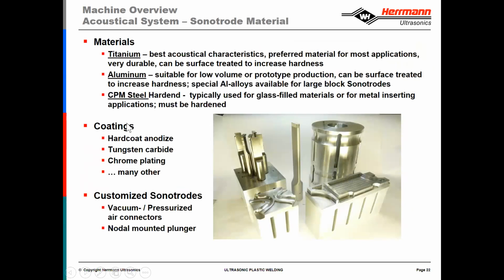The different materials that we typically use are either titanium, aluminum, or steel. I would say about 75 to 80% of the tools that we make are made of titanium, and then the other 10% in aluminum and 10% in steel, plus or minus. Titanium has the best mix of strength and elasticity. Aluminum is very soft, so it can have more amplitude or it can be stretched more than titanium. However, because it's softer, it can wear out faster as well. On the other end of the equation is CPM steel.